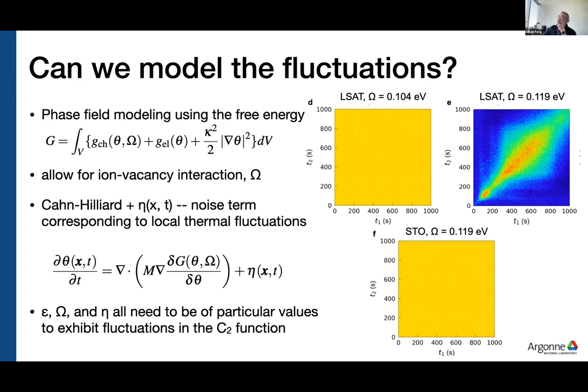So it's partially getting our two-time by capturing the right elastic term, but it doesn't capture the right time scale. And so the guys at Oak Ridge had to go more complicated and use this Cahn-Hilliard equation that I'm showing at the bottom of the slide. So they used the Cahn-Hilliard equation, which was originally developed for spinodal decomposition. And they had to add a noise term.